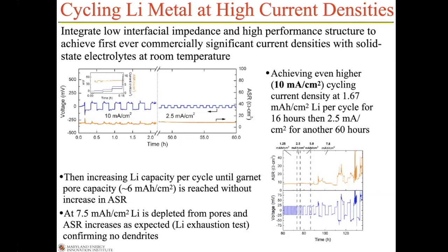And this is what's called an exhaustion experiment. The pore volume is 6 milliamp hours per square centimeter. So you'll notice very stable cycling until we get to the point where we're literally stripping 100% of the lithium out of the pores. When all the lithium comes out of the pores, it no longer has that conductive path, and now the resistance goes up. This is one of the experiments we ran for RPE to confirm that there were no dendrites with the lithium cycling cells.